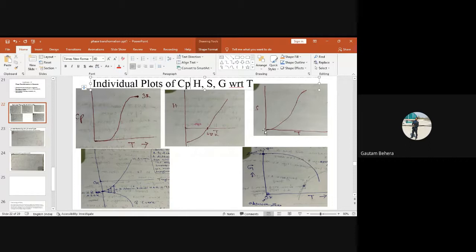So pure metals, pure elements, pure substances have only thermal entropy. But when we are dealing with impure metals or alloys or multiple components, a system having at least two components, then configurational entropy will come into the picture, right? Otherwise, there is no configurational entropy in pure materials or single component materials, right?